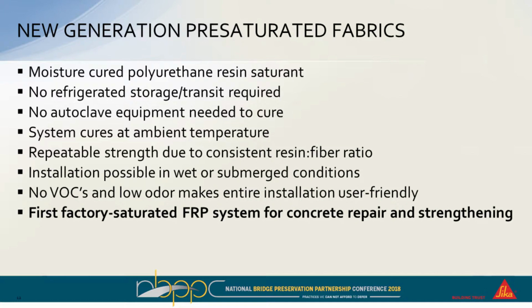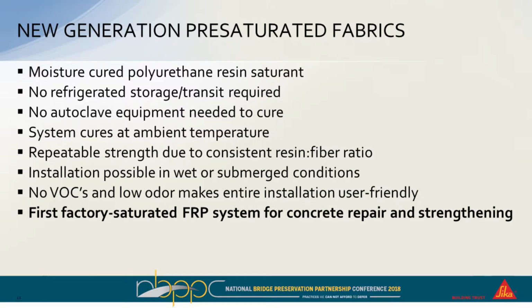Basically, it'll go anywhere from about 40 degrees Fahrenheit up to about 120 degrees Fahrenheit. So you have a very wide range of temperatures that it would work in. Repeatable strength due to the consistent resin to fiber ratio. Installations available, like I mentioned, even in very damp conditions or saturated concrete conditions.